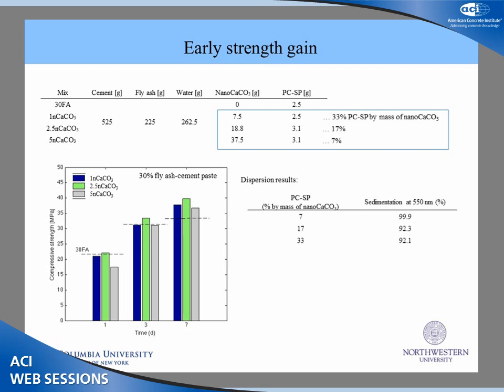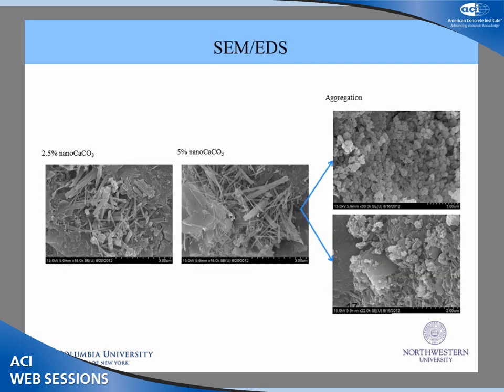And if we revert back to our dispersion results from earlier, we saw that 7% sedimentation was quite high. So the erratic behavior behind the 5% calcium carbonate particles mix can be due to issues of dispersion. And this was confirmed in SEM EDS results.